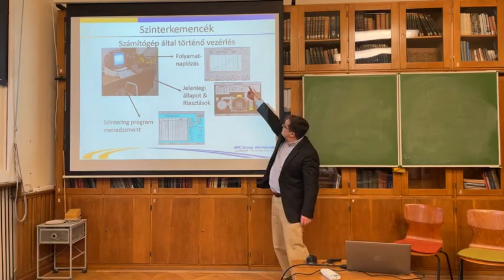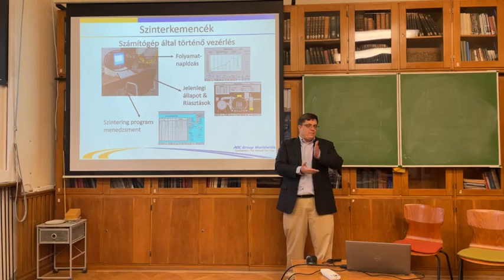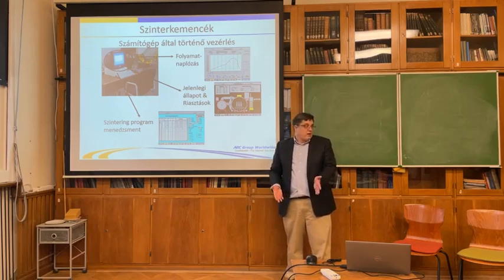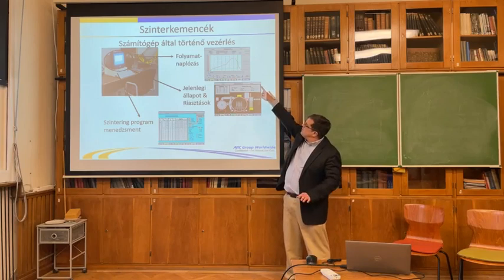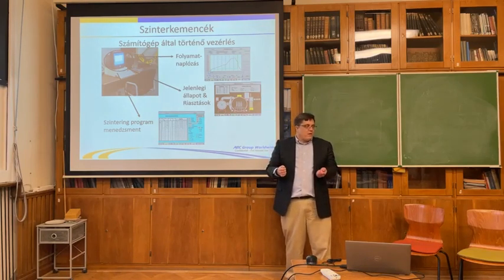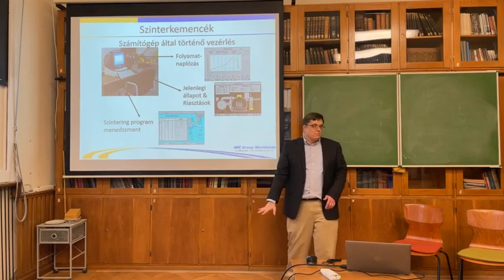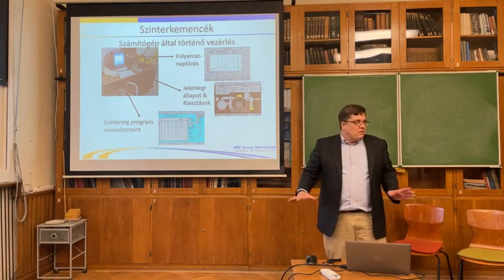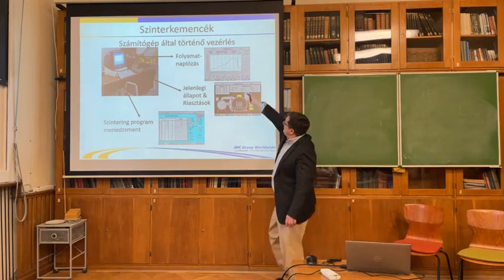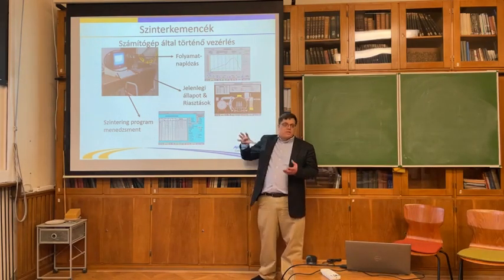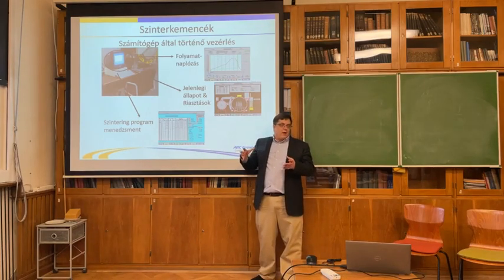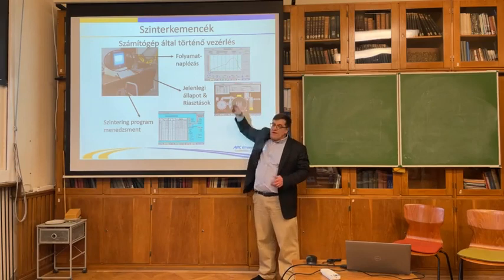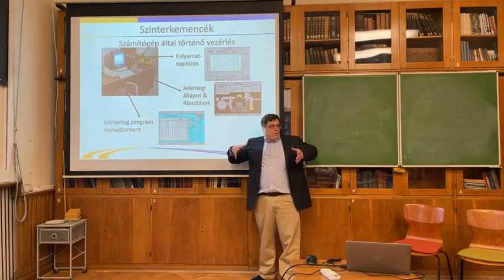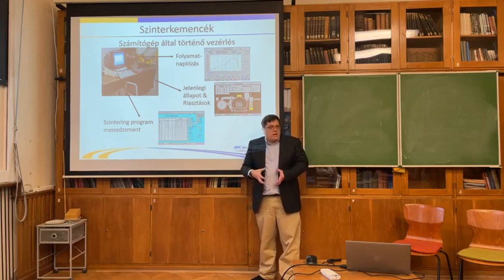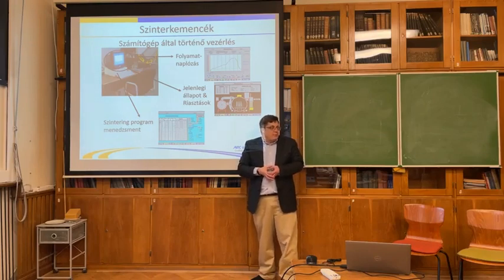And then at the end of that, we have what's called the static cool. Electricity cuts off, and it just cools statically, because it's still very hot at that point. Then at either 700 or 900 degrees, either argon or nitrogen turns on, and it brings it down. So that's a sintering cycle. But at the top there, that's where the shrink and the densification is happening. At that 1,000, that's where it's going. Once it starts that phase, it's still 20% bigger, but at the elevated temperatures, that's when it's fusing together. All that porosity you see is now getting eliminated through the higher temperature.